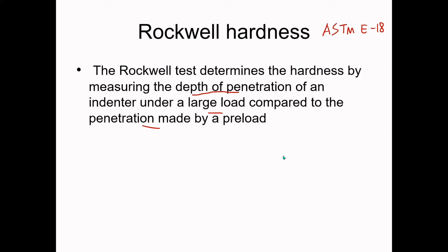The Rockwell test is designed as a method of hardness testing for rapid comparative analysis between different types of materials or samples. The depth of impression or indentation is measured and rated on a dial calibrated inversely into 100 divisions. A deep impression will result in a low value, which implies a soft material. A hardened steel ball is used at the end, with a diameter of 1/16 inch, 1/8 inch, 1/4 inch and 1/2 inch, and standard indenting loads are 60 kilogram, 100 and 150 kilogram.